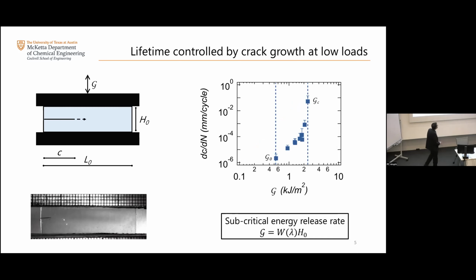So when you conduct that experiment, you can do it at different levels of G or at different levels of deformation. And what you actually record is the crack growth per unit cycle. You can think about it as your velocity. And then you have basically three regimes. You have a G0, which is a material property, which people call the fatigue threshold, at which the amount of energy that you apply is so low that the crack effectively doesn't move, okay?